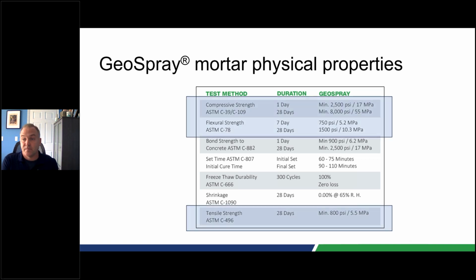I wanted to highlight a couple. So in the market of pipe repair, it's really a standard that the compression strength of the materials is approximately 8,000 PSI minimum. That's an across the board standard you will see. There are some good benefits about that. Those are very high strength materials. We'll talk a little bit about quality control later. You have to be a little careful when you test stuff that has that high compressive strength that you do it right, but those are the industry standard.